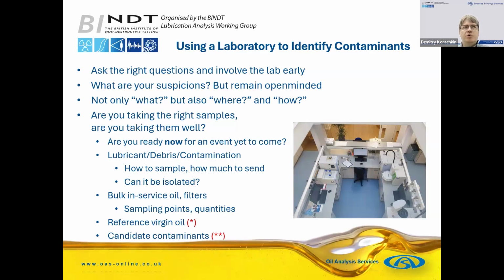So when you send a sample to the lab talking about contamination, you may give your suspicions, or we think it's that, but remain open-minded and allow the lab to suggest test suites, which may do an overall condition. We had a sample come in where a client wanted to check if there was AdBlue in fuel. We got that fuel sample. Normally fuel is a fairly clear liquid, maybe slightly yellow or slightly red if it's red diesel and so on. It was black. We tested it. They allowed us to perform the standard test package rather than just looking for AdBlue.